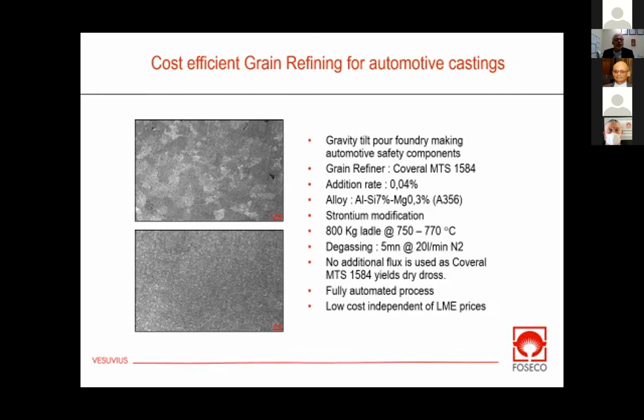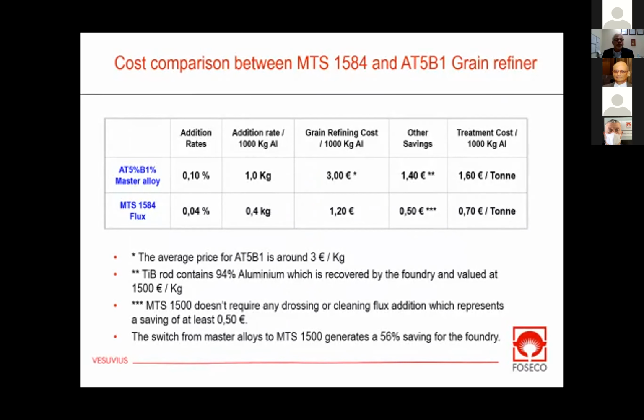Many of these gravity foundries have switched from master alloys. I'm showing a cost evaluation we did a few years ago in Europe with one of those foundries, where we compared. They were using roughly 1 kilo of Tibor master alloy per ton of melt, and we were able to reduce this to 400 grams because our grain refiner has a higher percentage of titanium boron. So we're able to reduce the addition rates and offer much stronger grain refining, achieving a much finer grain than they would otherwise achieve with the master alloy.